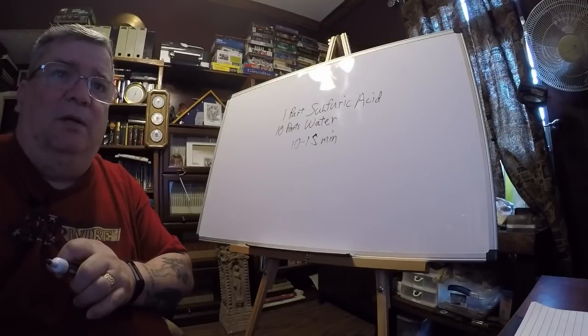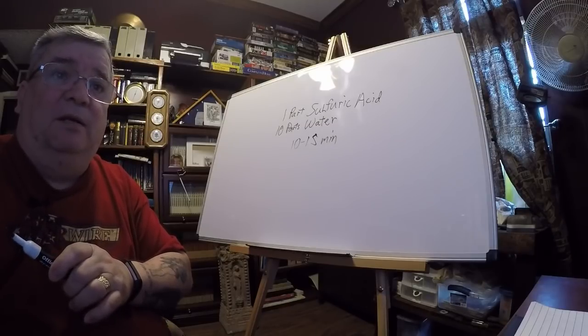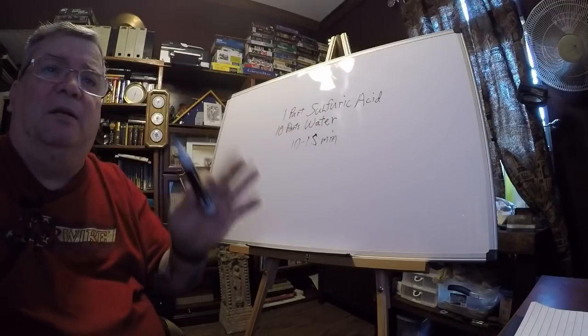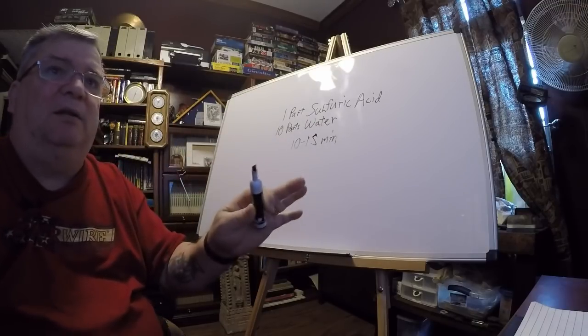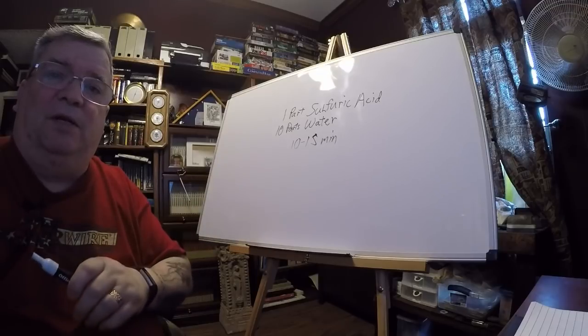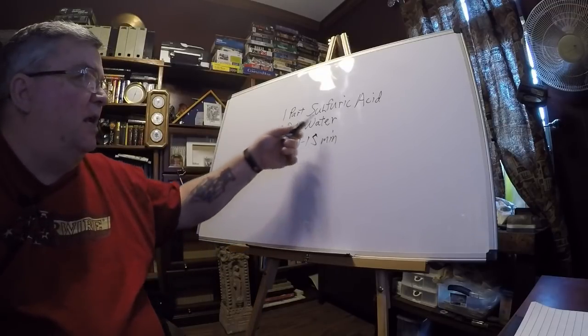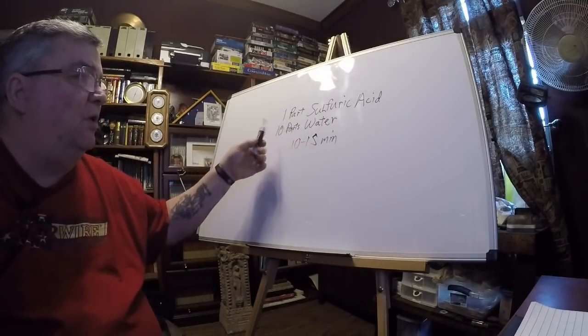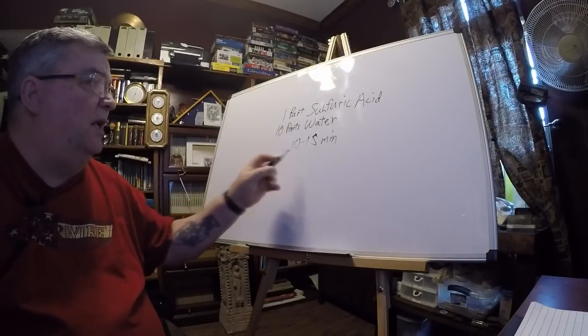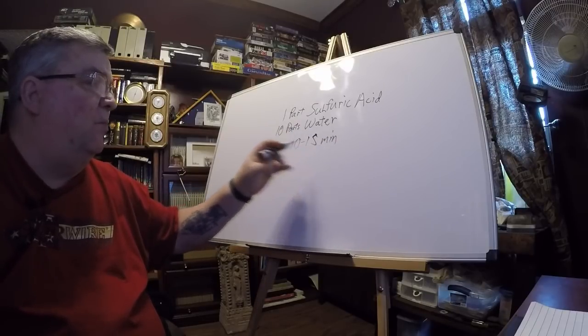You form steam at 212 degrees Fahrenheit. Let's pretend I'm making up a temperature. Let's pretend it's going to be 150 degrees. If you have this at a heated up temperature, you don't have to have it in for 10 to 15 minutes anymore.